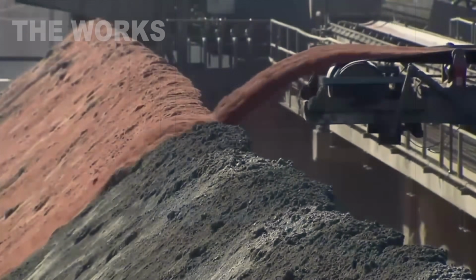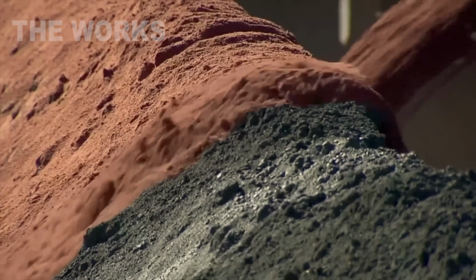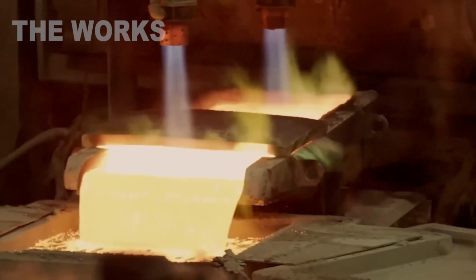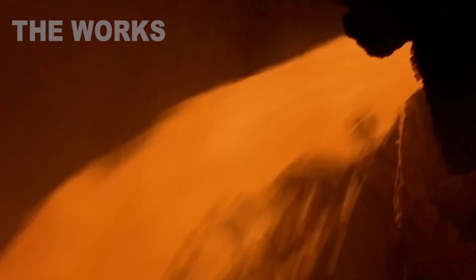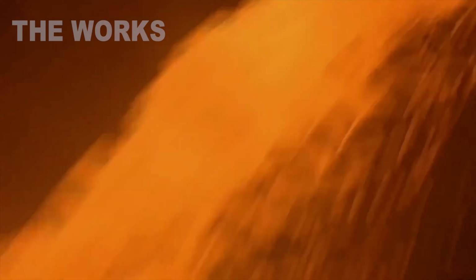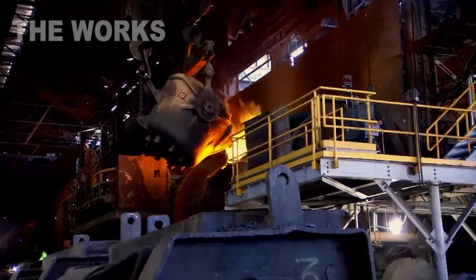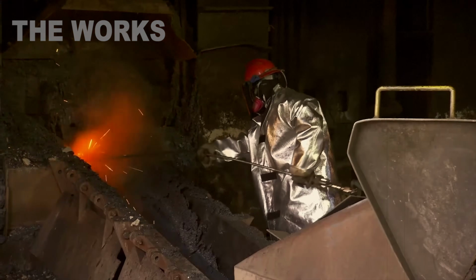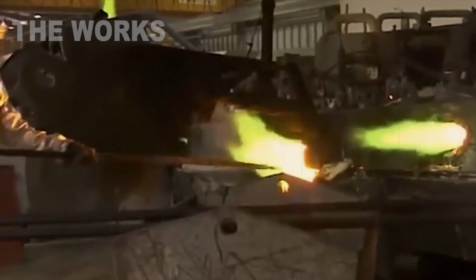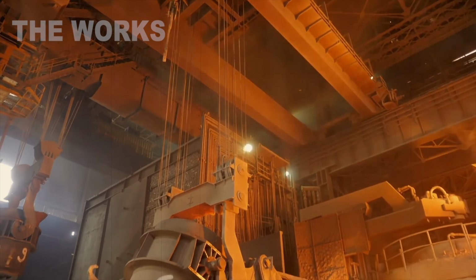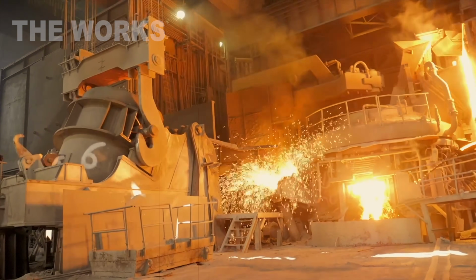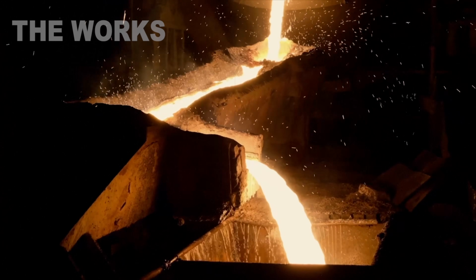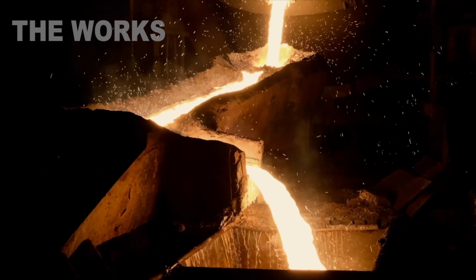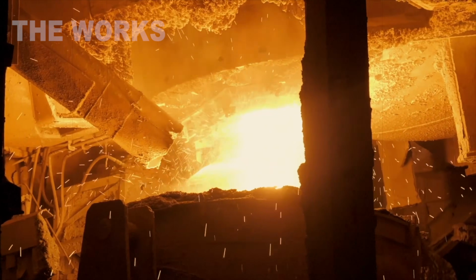The concentrate heads to a copper smelter. Here it's turned into pure metal. First stage, roasting. The concentrate is heated to 1300 degrees Fahrenheit in the presence of oxygen. Sulfur burns off as sulfur dioxide gas. What's left is sinter, a mix of copper and iron oxides. The sinter gets loaded into a reverberatory furnace. Temperature 2200 degrees. Silica flux is added. Iron bonds with the silica and floats up as slag. Copper settles at the bottom as matte, an alloy that's 50% copper.